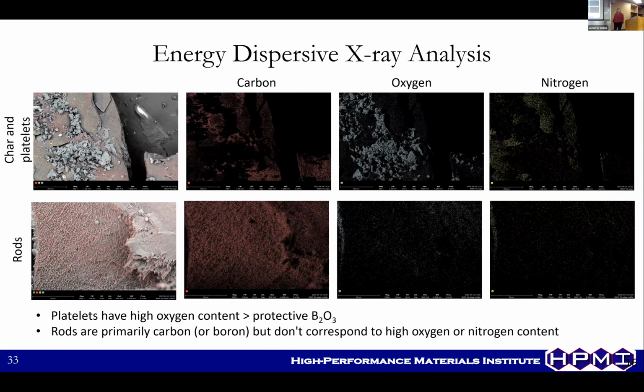So the next question is, what are they made of? We did some EDS to find out the chemical composition, and saw that there's your charred platelets and here's your rods: carbon/boron, because carbon and boron can sometimes be difficult to distinguish with EDS. So that's carbon/boron, oxygen and nitrogen. The platelets clearly have a very high oxygen content, but they still have nitrogen, which means we still have the existence of BN, which means that this is likely protective B2O3. So we can make some of those conclusions from EDS, and then the rods are primarily carbon or boron. They don't have high oxygen or nitrogen content, so right now we're a little unclear. So potentially just amorphous boron.